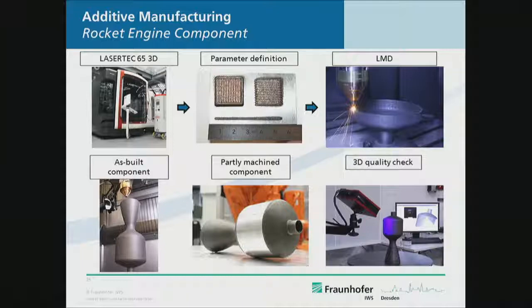with building the part. Now, this is a recent example coming out of an ESA project where we were contracted to build a rocket part. The part itself, shown in the picture on the bottom left-hand side, has a size of about 40 centimeters in height and a largest diameter of probably 20 centimeters or so. It's built from a nickel-based alloy, and it's built exactly in this machine here. So, of course, it's a multiple-step process, starting with the design of the part first, and then the parameter definition for the material's deposition, followed by the LMD process itself.